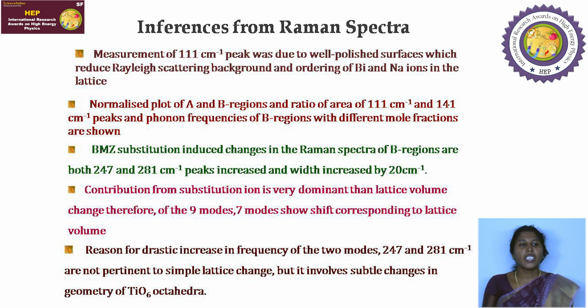Regarding the B region, we can see 2 modes in the frequency range 247 and 281 centimeter to the power minus 1. Here the peak frequencies are increased and the width is also increased by 20 centimeter to the power minus 1. So this is related not only to the lattice change, but also to the subtle change in the geometry of the TiO6 rotational vibrations. Out of the 9 modes, in 7 modes we can see the shift, which is due to the volume change due to the substitution of BMZ in the NBT lattice.